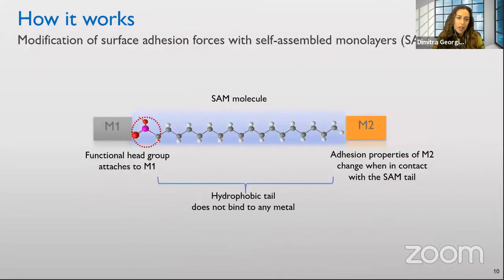How does it work? The main attribute of this technique is that it is based on the modification of surface adhesion forces with self-assembled monolayers. A self-assembled monolayer is a molecule like the one shown here, which bears a functional head group, and this group has an affinity for a specific metal. For example, it can be a phosphonic acid, which attaches to the native oxide of aluminum oxide or titanium oxide, or it can be a thiol group, which has an affinity for gold, for example. The rest of the molecule is a long hydrophobic tail, which does not bind to any metal.